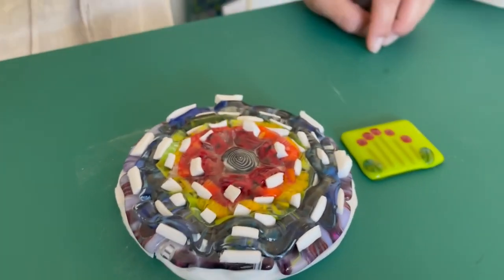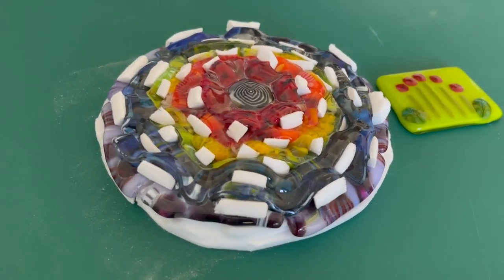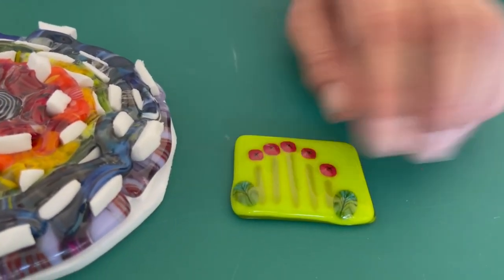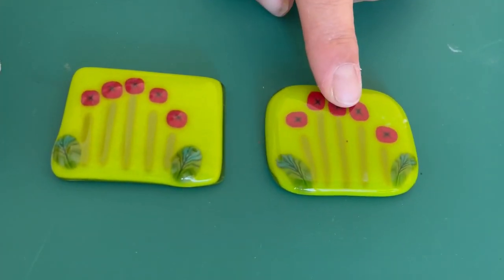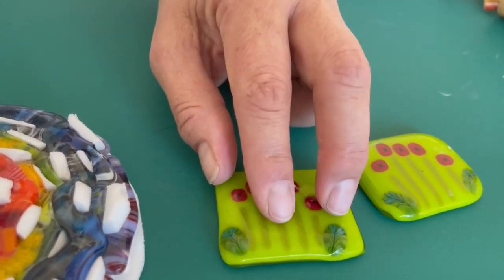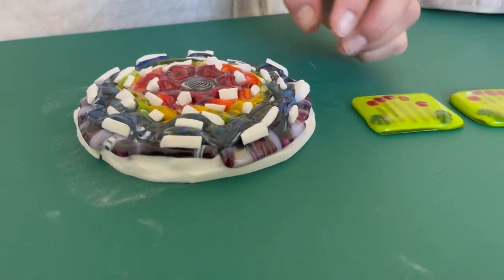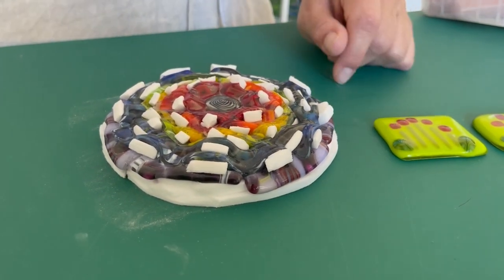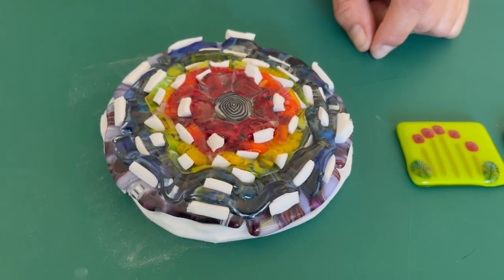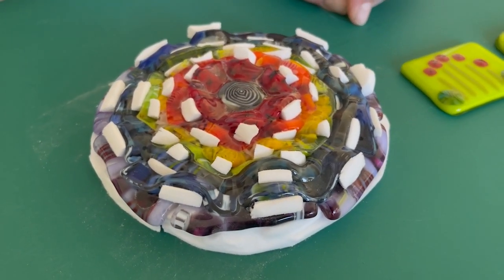So here this is out of the kiln. Now this is a great lesson guys — I have a kiln that fires hot and it's firing really hot. I think there might be a problem with the thermocouple on it, because this went to a 730 tack fuse, which is a very low tack fuse. I had this in the kiln as a sample to show people at workshops the difference between a full fuse and a tack fuse, and that is a blooming contour fuse. This is why I say I hate giving firing schedules because it really is kiln dependent. So I wasn't planning on it looking like this — I'm going to try and clean it up and clean the fibre paper out and hopefully end up with something that looks like a rainbow flower.